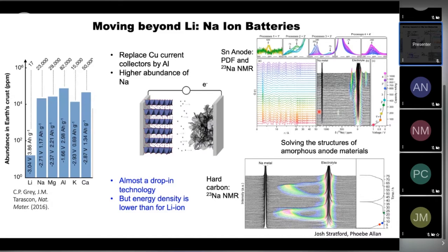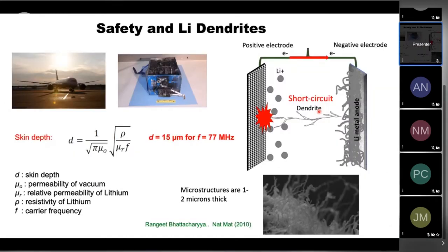So what about safety? The Dreamliner battery was an example of a new lithium ion system that had safety issues a number of years ago and caused the Dreamliner to be grounded for a full year while they sorted out the battery issues. And one of the major sources of the problem, at least, was believed to be associated with the formation of lithium dendrites. So even when you charge graphite and you charge it too fast, the lithium hasn't got time to intercalate into the graphitic sheets. And instead it forms these mossy lithium structures that, if they start to grow towards the positive electrode, can cause a short circuit.